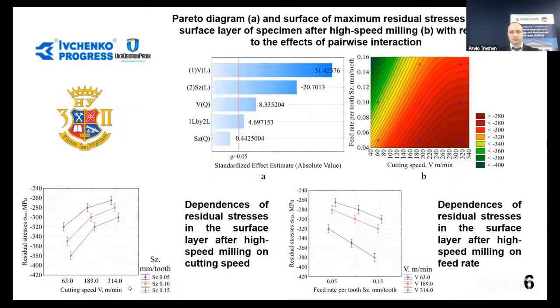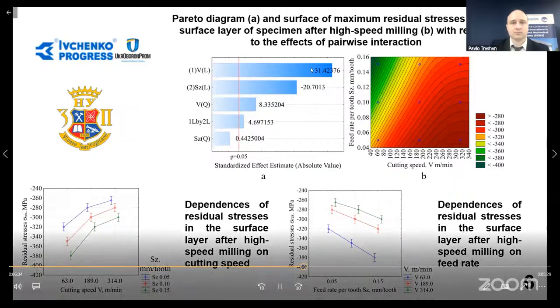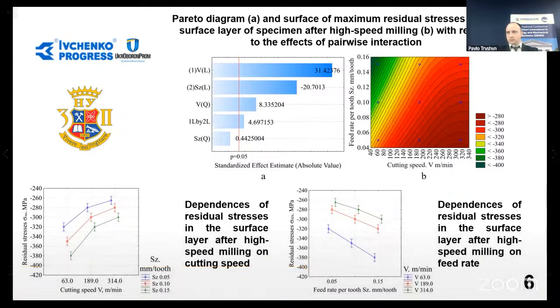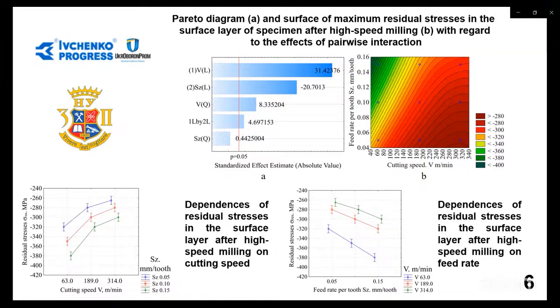The greatest influence was exerted by the cutting speed. The influence of cutting speed and feed was multidirectional. Increasing the cutting speed led to a decrease in the value of compressive stresses, while increasing the feed rate per tooth was accompanied by their increase. Analysis of the response surface of the investigated value showed that the effect of cutting speed, contrary to the feed rate per tooth, is non-monotonic.